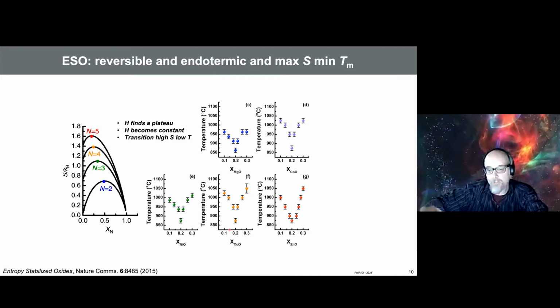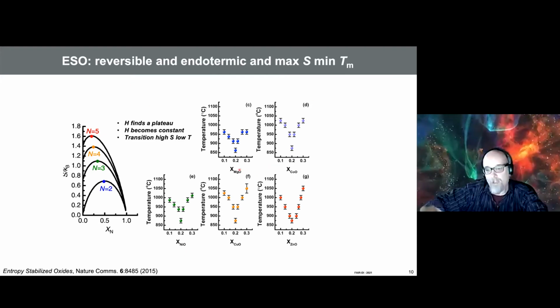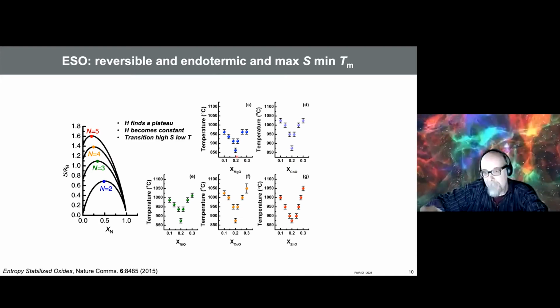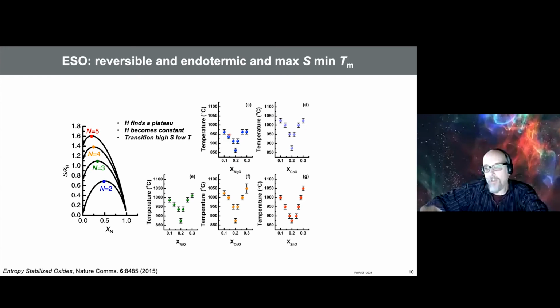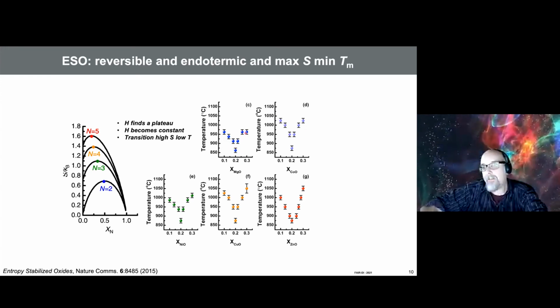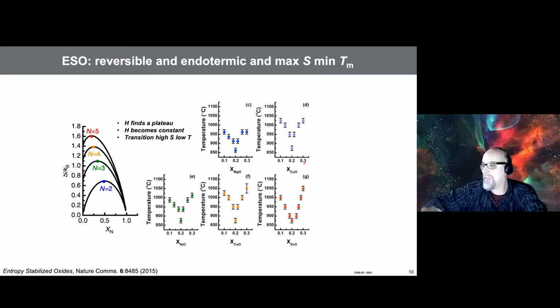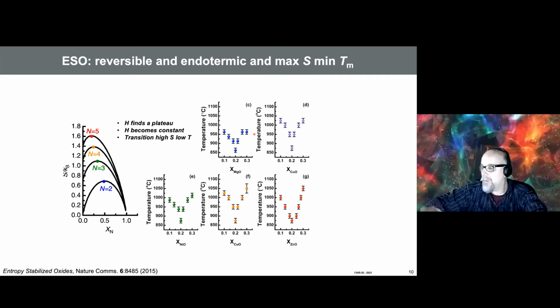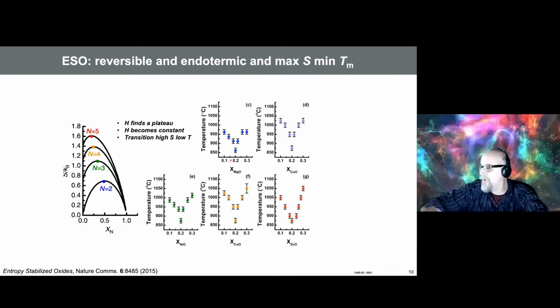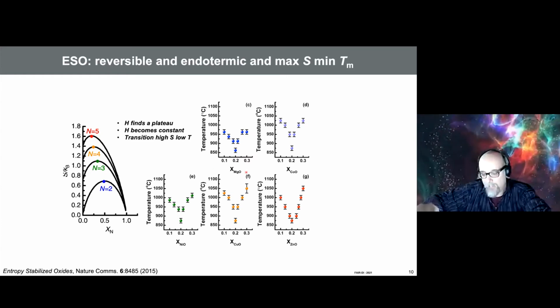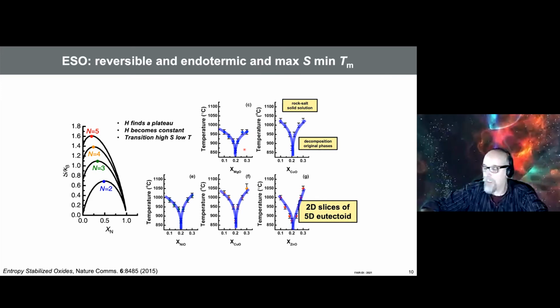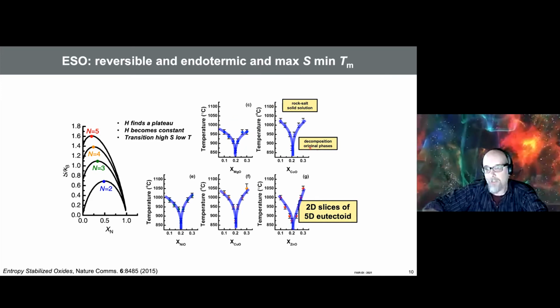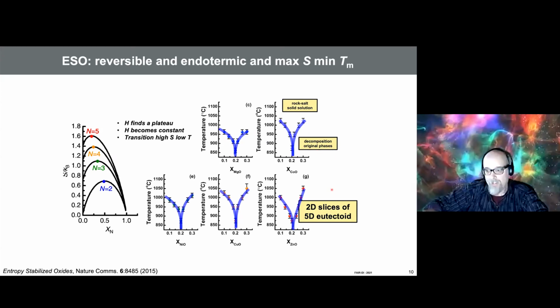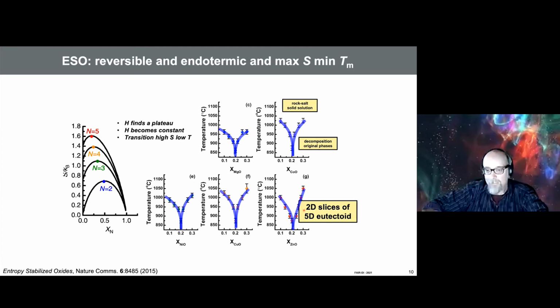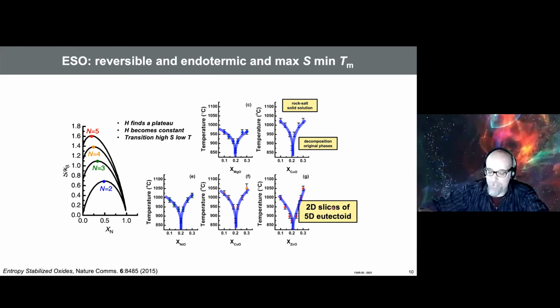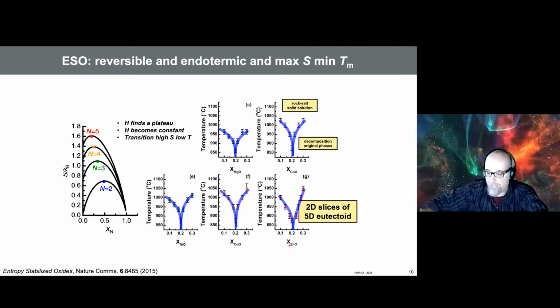So you see that we did some sort of cross-validation by changing the composition of the constituents, and you have T min where S is max. Okay, so when you go off stoichiometry, well, off equicomposition, the transition temperature increases. So that is an example of experimental big data, because every one of those V shapes took many experiments. Then eventually everything went online, and then was recalculated, and all the data is available. So this is another example that is really entropy driven. On top you have rock salt, and on the bottom you have the composition of original phases. So if there are thermodynamists like me, those are 2-dimensional slices of a 5-dimensional eutectoid. So a solid solution above and the composition on the bottom.